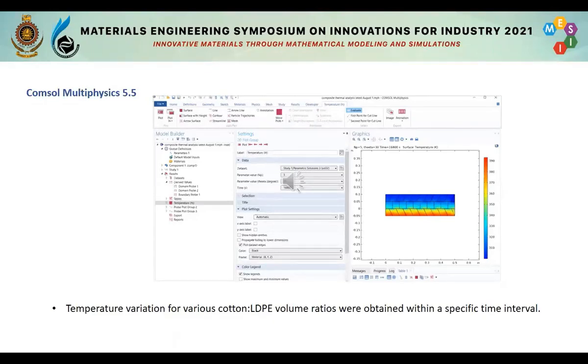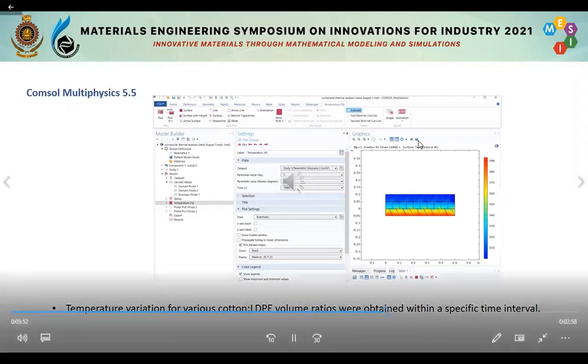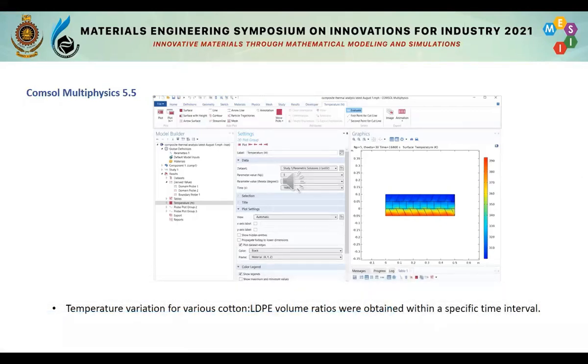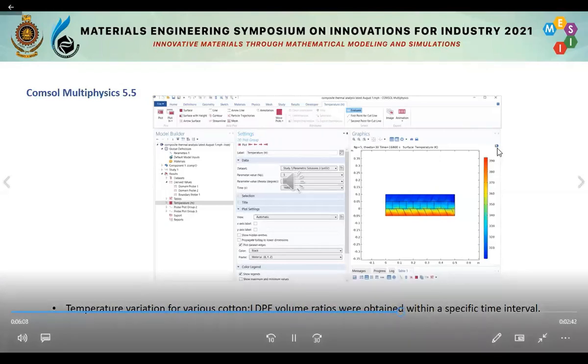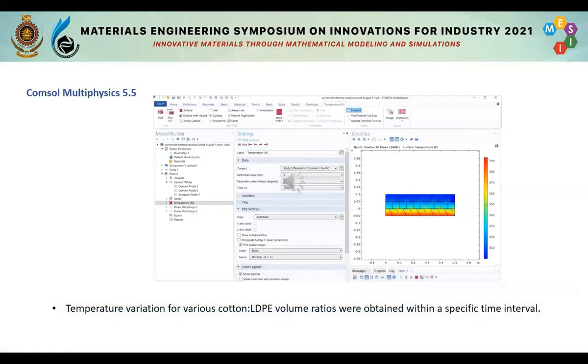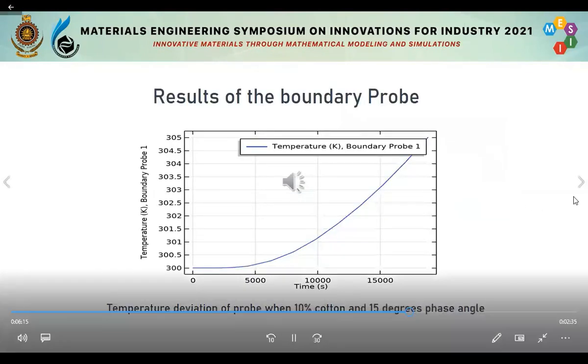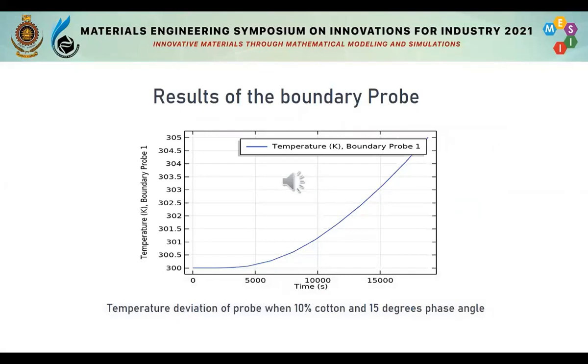While changing the percentage of cotton and LDPE, we studied the variation of top surface temperature. You could see that the bottom surface, the surface which we kept at a higher temperature, has a steep temperature gradient, which is denoted by red color in this figure. And when it reaches the other end, the temperature gradient reduces, which is shown by blue color. So we studied the temperature gradients by changing the percentages of LDPE and cotton. Then, considering the results of the boundary probe, which is kept at room temperature, you could see in this graph that when the time increases, the temperature increases.